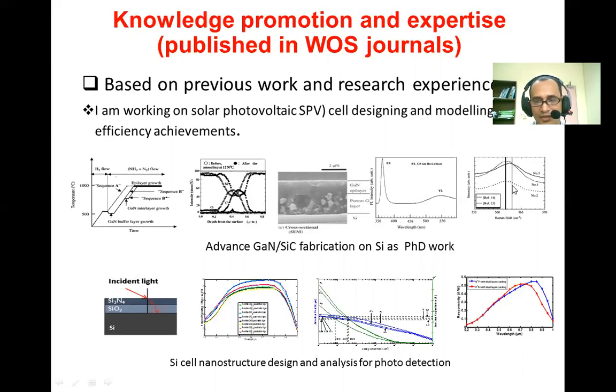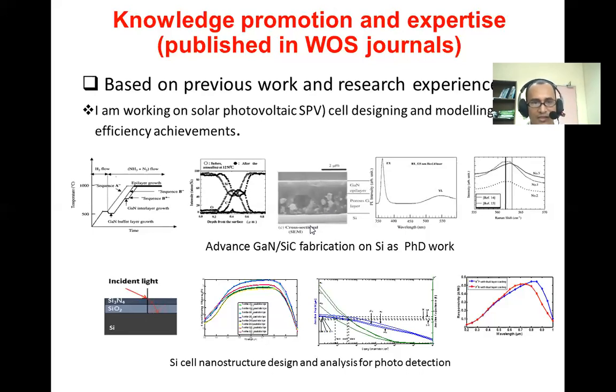In the photoluminescence data, you can see a very sharp peak indicating better quality of gallium nitride deposited on silicon. The stress of this material system, favorable for optoelectronic devices, varied due to growth conditions and thickness. The porosity made it thermally less effective on the cap layer, which reduced stress and allowed gallium nitride growth of about 2 micrometers thickness without cracks.